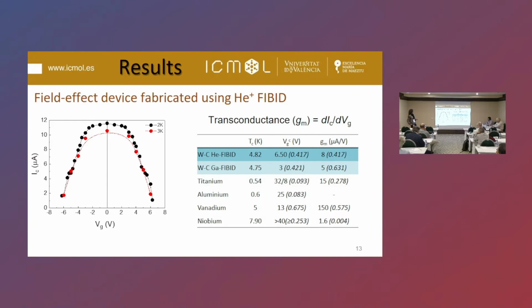And just having a look at the transconductance, which is a figure of merit of the performance of field effect transistors, we obtain similar values, comparable with the transconductance values obtained in other superconducting materials, but even using a lower critical gate voltage. And even taking into account the critical current and the critical temperature of our devices, in principle, the applicability of these devices is in a wider range of temperatures compared to the other superconductors.